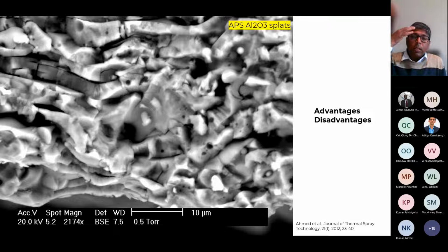This is a typical fractured surface of the coating flake. What we did was a deposition of alumina, which is a very brittle material, using the air plasma technique, and took the flakes off the substrate and then broke the flakes in cryogenic condition. So we just wanted to see how the cross section looks. It is not a polished surface, it is a fractured surface.